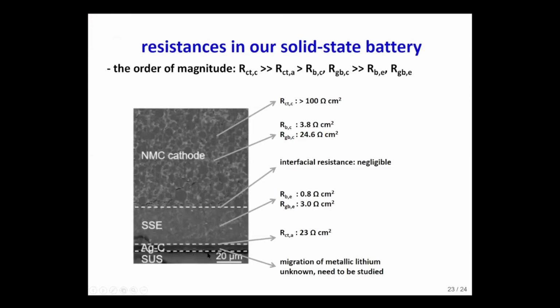I mean, this is the interface here? Yes. Yeah, because I think all the components below this line would be metallic. So there will be two kinds of transport phenomena here. One is the electronic conduction, and the other is the movement of lithium metal. So I don't think this interface is an issue because only the electronic conduction happens here, and maybe this interface is associated with the reduction of lithium ions. So there's going to be some resistance, as I showed you, but I don't think this interface is involved very much in the whole process of the polarization.